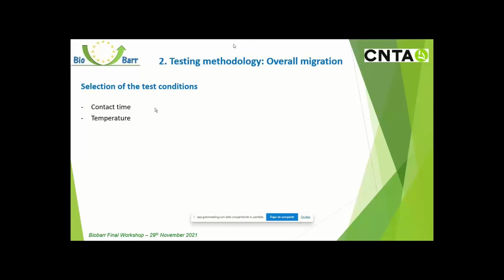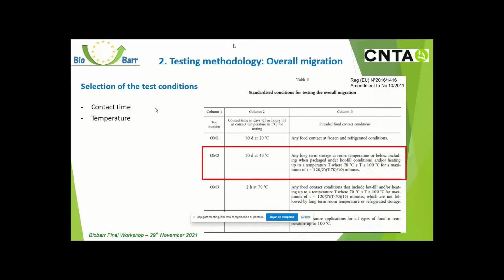Regarding the selection of the test conditions, we have to select the contact time and the temperature. It's also covered by the legislation, and there are some standardized conditions for testing. In our case, we selected 10 days at 40 degrees. And we also have to fulfill the legislation, so there are some limits for the overall migration. The limit is set at 10 milligrams per square decimeter. And in the case of specific migration, there is a maximum permitted amount of a given substance released from a material. And if there is no maximum permitted, there is a restriction, and the limit is set at 60 milligrams per kilogram.